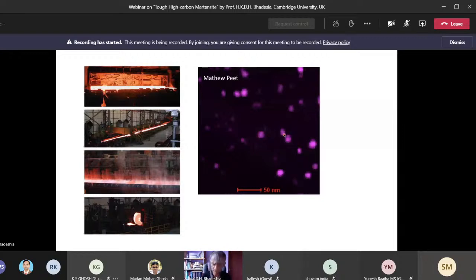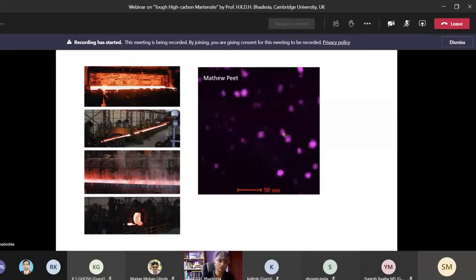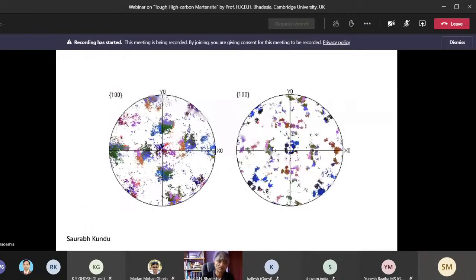So now I'm going to show you the evidence that what we have done has achieved a very fine martensite plate size. And I'm going to show you this in a completely different way from normal. I'm not looking at the length of a plate, but looking at a single austenite grain and the crystallographic orientations of the martensite within that grain. And in one case, I'll show you the austenite which is not deformed, and in the other case the austenite which is deformed. So this is a pole figure where we are plotting 100 poles of all the martensite plates within one austenite grain which is not deformed, right? And this is exactly where we expect the peak intensities if you follow the orientation relationships between martensite and austenite. So there are 24 variants of martensite inside this grain of austenite.